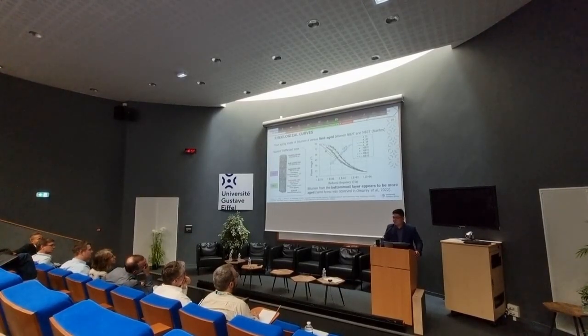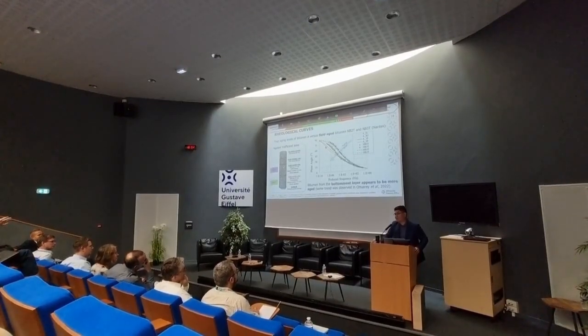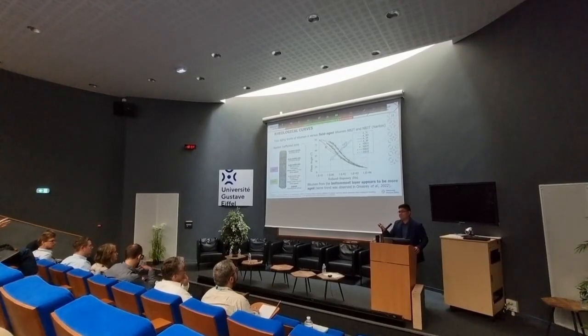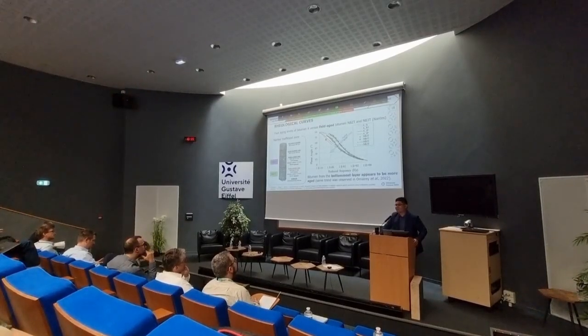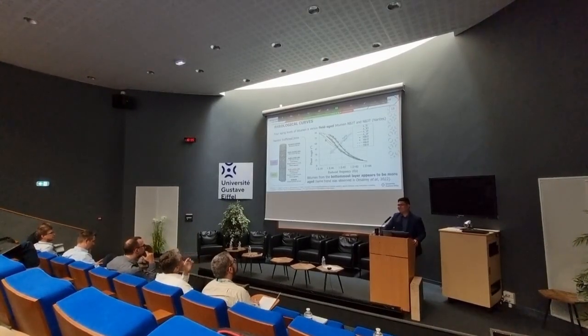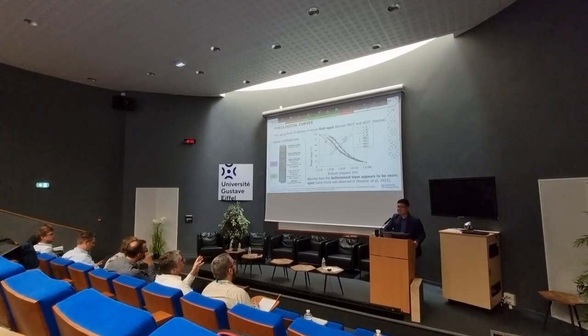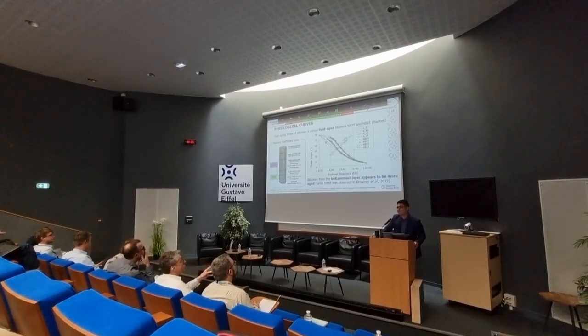Yes, it was Strasbourg and Dijon. Strasbourg was 40% RAP, and Dijon was 10%. In this case, I don't remember the original documents, but I remember that for Strasbourg they had used a softer bitumen, a 70/100 bitumen, to do the reformulation with RAP. I don't know much about rejuvenator properties to renew aged bitumen. Even without rejuvenator, when you want to use RAP, you mix old bitumen with a new one that is softer, sometimes much softer. But yes, is it enough?